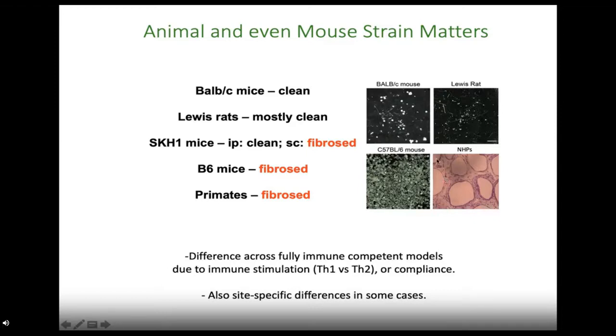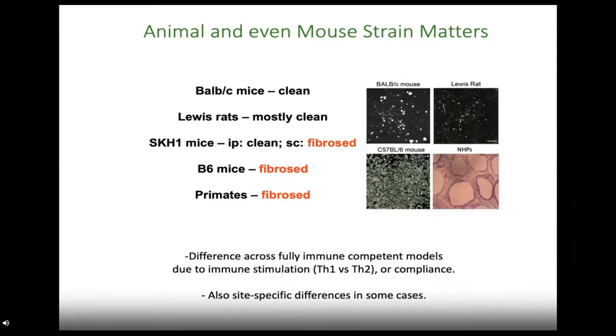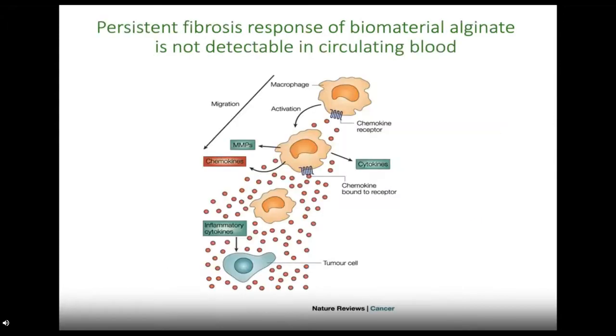In the monkeys, not only do you see fibrosis, you actually have extensive embedding of materials into surrounding tissue — which we also see in the Black/6 mice over time. This usually happens with non-collagen-capsule-encapsulated fat pads as opposed to lobes of the liver, kidney, or spleen. The reason for this is that fat in your body does not have collagen wrapping around the outside the way that primary organs do, and fat pads are highly vessel-laden — trafficking highways for the immune system.